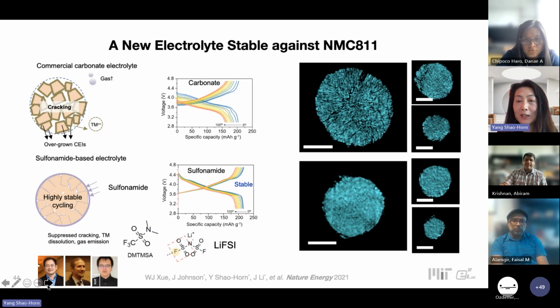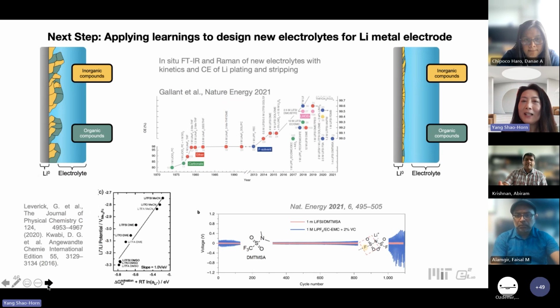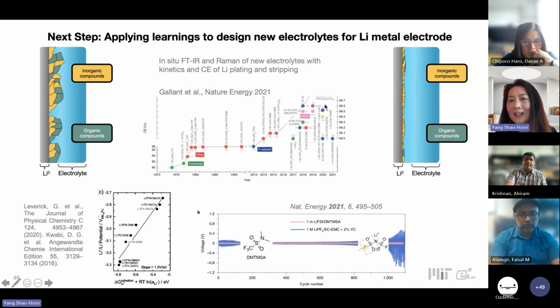And so this is essentially one opportunity, one example of designing an electrolyte based on a fundamental understanding of the reactivity between the electrolyte and the surface. And similarly, we can also tackle the challenges of lithium metal reversibility or stability utilizing a similar idea. Right. So, for example, if you look over the past few decades, if we change the liquid electrolytes, right, the Coulombic efficiency of lithium stripping and plating can increase significantly, right, up to maybe